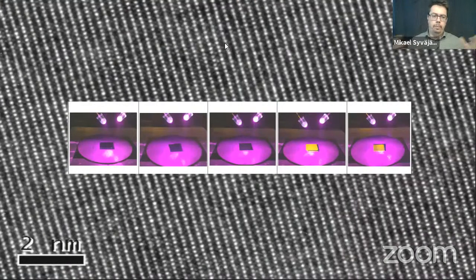Here you see some images of samples which are excited by a near UV LED, two on the top here, and then we have the silicon carbide small square. With different changing conditions, we actually have light coming out. This is one of the layers, the warm white layer, where we could actually have luminescence coming out from the silicon carbide material we have been growing, and it comes out at room temperature. So it was not a theory.